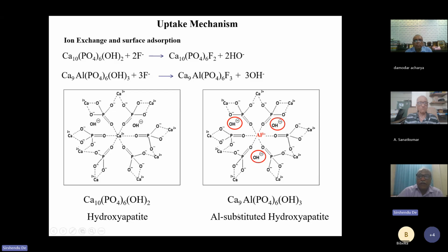So we developed this aluminum substituted hydroxyapatite phase in the laboratory using commercial grade chemicals. Now this material is produced in powder form. Now the powdery material cannot be used as a fixed bed for the removal of fluoride. So what we did, we developed this particular phase in situ with a porous carbon scaffold. Here the porous charcoal, that is commercially available porous carbon, we use as a support material, where inside the pores and on the surface, this aluminum substituted hydroxyapatite is generated in situ.